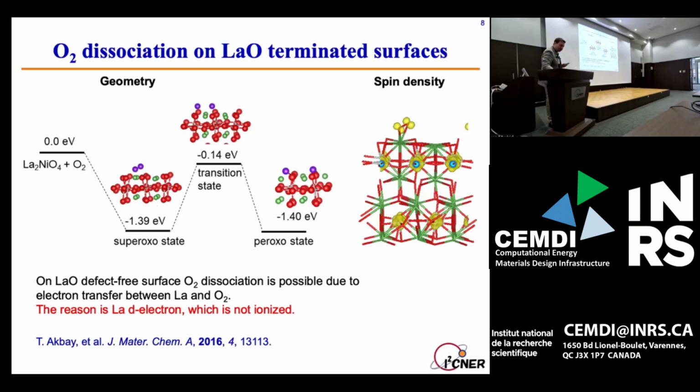So we were immediately challenged when we had these results by our experimental collaborators, who said, well, that's very interesting, it's a nice theory. However, how about lanthanum nickelate? That's a Ruddlesden-Popper nickelate. And as a Ruddlesden-Popper oxide, lanthanum nickelate is known to have an excess of oxygen, more than stoichiometrically needed. So all the vacancies within the material are usually annihilated, or we would not have any vacancy composition, yet the material is showing experimentally pretty good exchange with the oxygen from the atmosphere. Well, we wanted to see what is making it special.